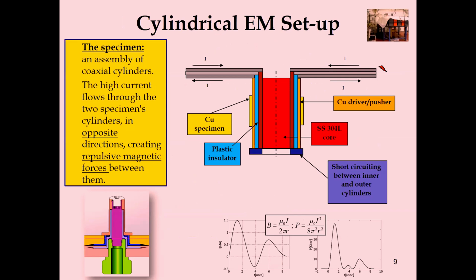So the cylindrical setup we're using, instead of having the planar specimens, which I was showing before in that small cartoon, now we're looking at an assembly of coaxial cylinders. The high current is flowing now in the axial direction of the cylinders. It's going through one cylinder and coming back through the other. I'm going to show this cartoon just like before. So here's the current. It's coming down through the middle rod and then returning through one of the cylinders, and they're pushing now inwards, compressing the inner rod and expanding outwards the specimen.